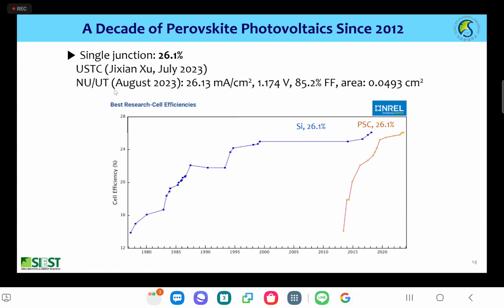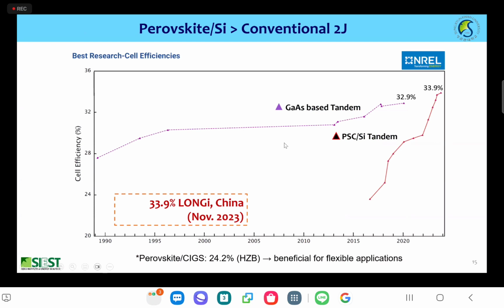I was told that this efficiency is really the same as the silicon single junction solar cell. Furthermore, if you put the perovskite on the silicon bottom cell, then a certified efficiency of 33.9% was achieved, which is the highest so far among the dual junction solar cell structures.